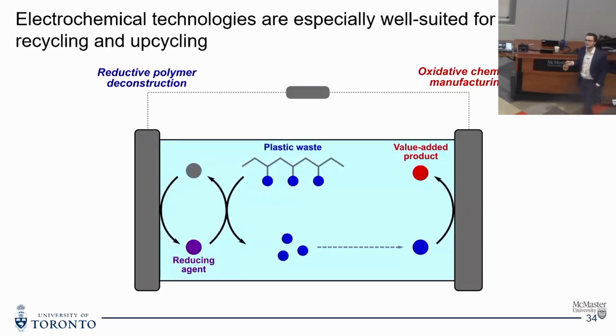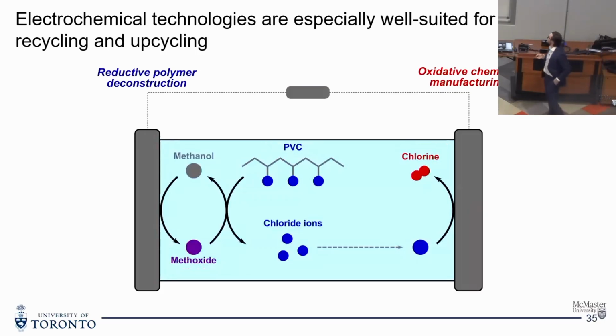And so the system I eventually settled into was using this framework, breaking down PVC, using methoxide as a reactive base to cleave this carbon-chlorine bond and liberate chloride ions. And then when we have chloride, we can readily oxidize that chloride to chlorine, just as a one-electron oxidation of each of those chloride ions, and get us to commodity-scale chlorine, which has a huge market in the world. And as a tandem, all chlorine today is already made with an electrochemical process. So this is something we know can be scaled, right?